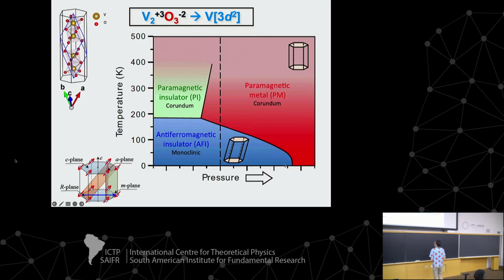And this is even more beautiful and complicated than that. This is ambient pressure. If we look not only at what happens as a function of temperature at ambient pressure, but also at what happens as a function of pressure, we see that we can go from a paramagnetic metal to an antiferromagnetic insulator or to a paramagnetic insulator, and we will also have, in this case, a corundum to monoclinic transition, or in this case, just a purely metal to insulator transition without change in magnetic state or in crystalline lattice.